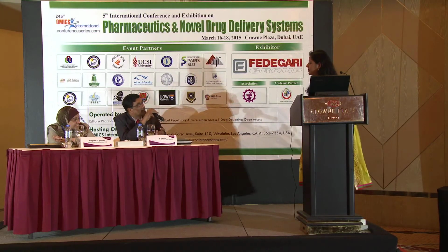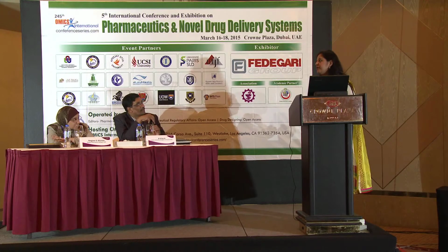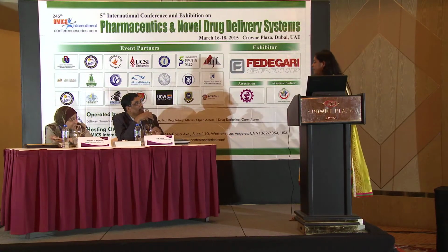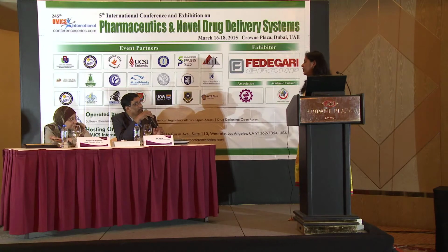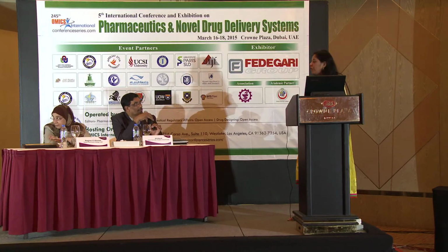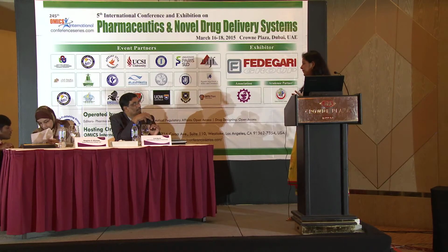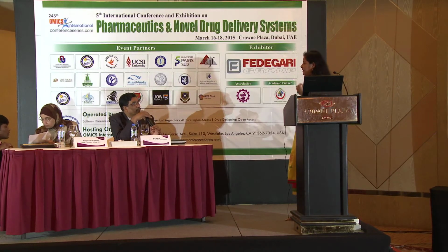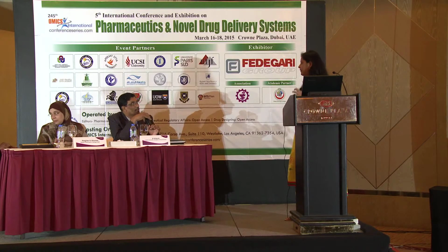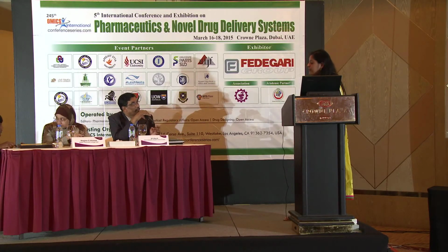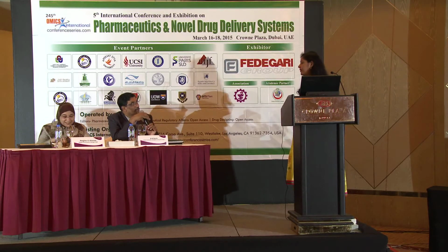What about the stability study? The stability studies did show that since curcumin is highly photo unstable, when we incorporate it into the SLNs, the stability is enhanced, maybe because of the light protective capacity of the SLNs. Have you studied the temperature effect? Yes, we have done. It's stable till 70 degrees.